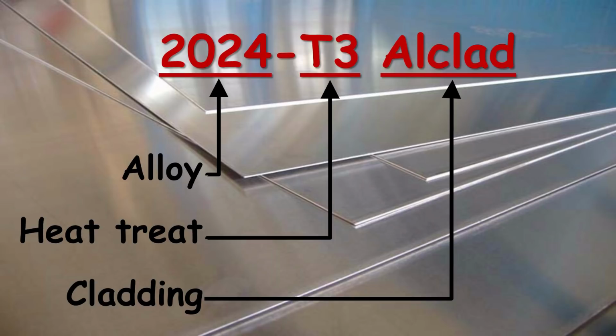And it's there to protect the material against corrosion, because the 2024 alloy is very susceptible to corrosion. If it's exposed to moisture, it will corrode, because the aluminum and copper make a pretty active corrosion cell if there's an electrolyte added to the mix. Whereas pure aluminum, when it's exposed to air, turns into aluminum oxide, which is a very, very good protective layer.